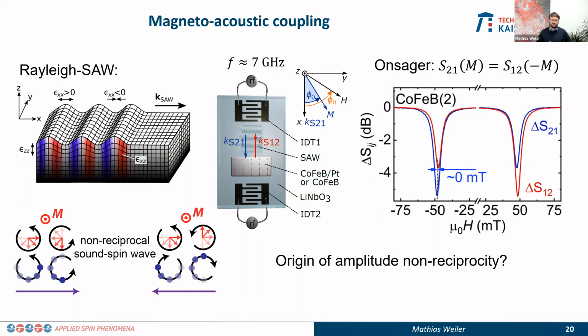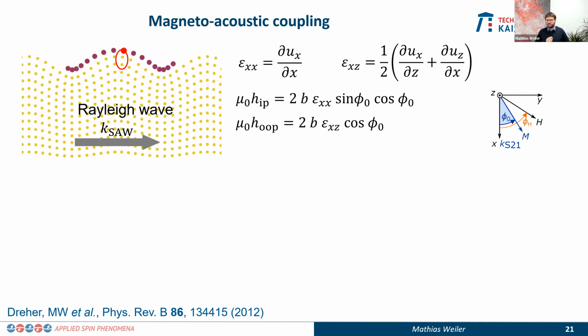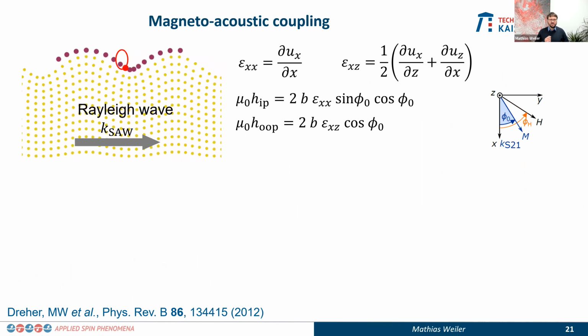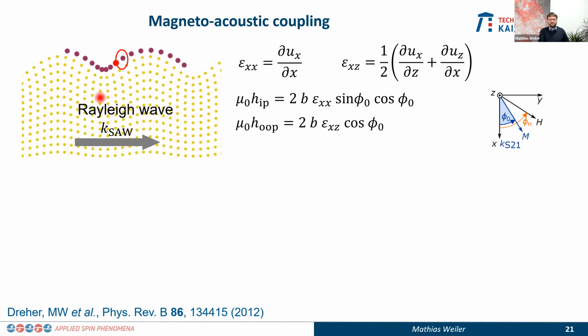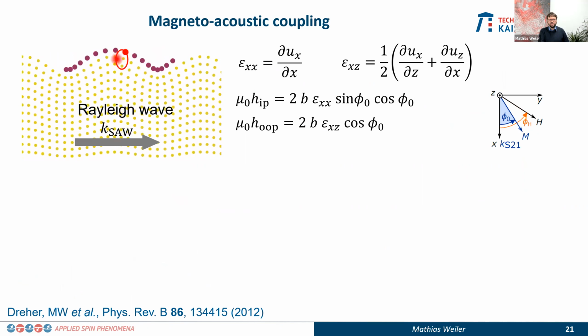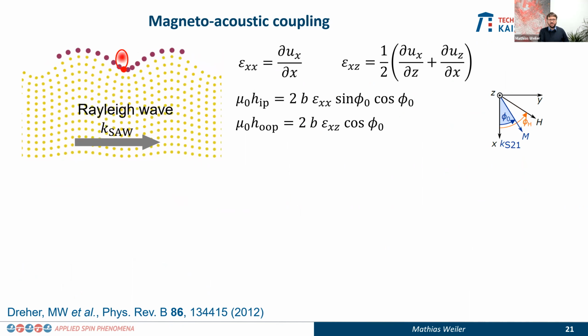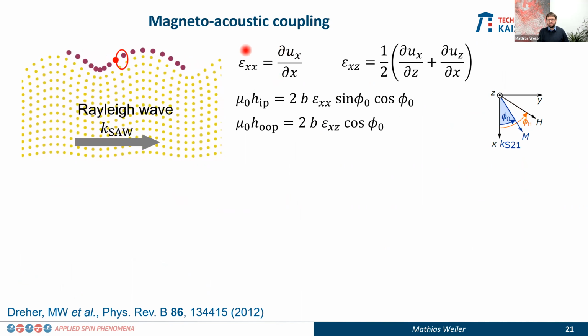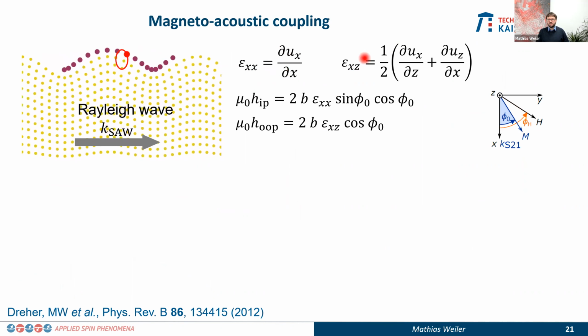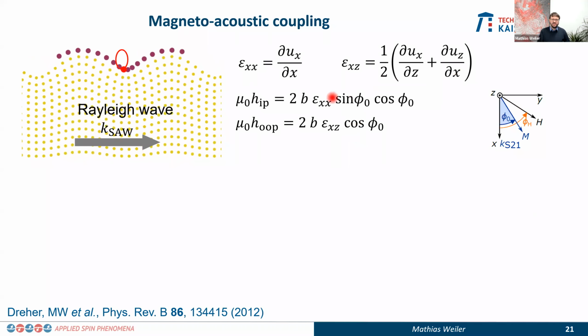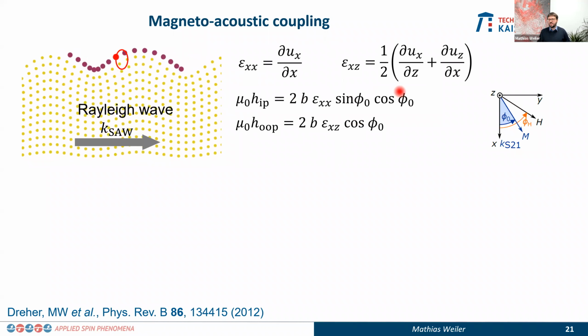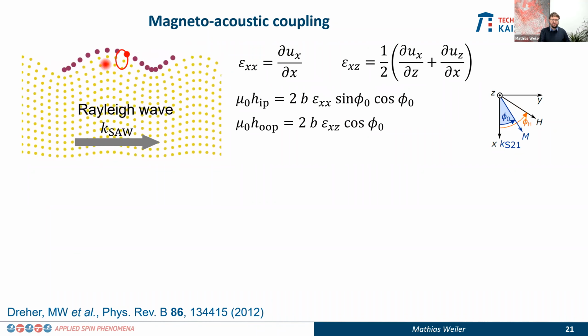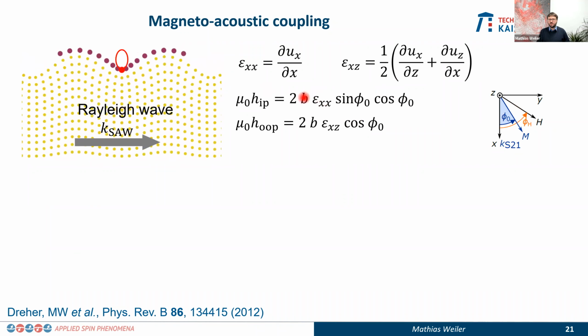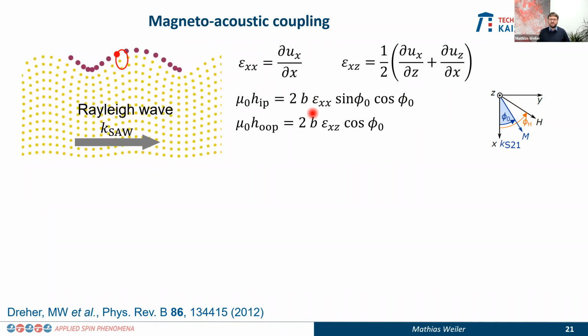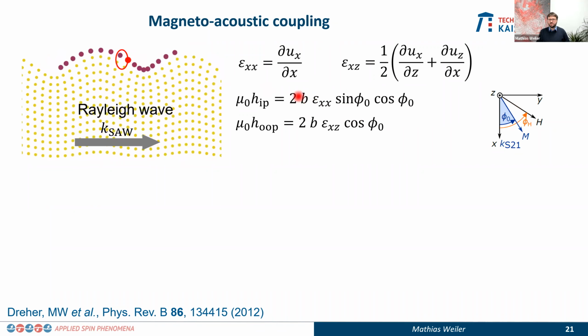Another question is, well, it's allowed by symmetry, but why is it now really non-reciprocal? Okay? Well, the model that we use to explain the non-reciprocity goes as follows. So we start from a Rayleigh acoustic wave. And that means we have the lattice motion on a circular or elliptical trajectory at the very surface of this material. And that means there are strain components that are pure strains and that are shear strains over here. And we can write down the effective field that is generated by the magneto-elastic interaction. So the effective field that this thin magnetic film sees here, because you change the strain and because there is spin-orbit interaction in the magnetic thin film, with B the magneto-elastic coupling parameter.